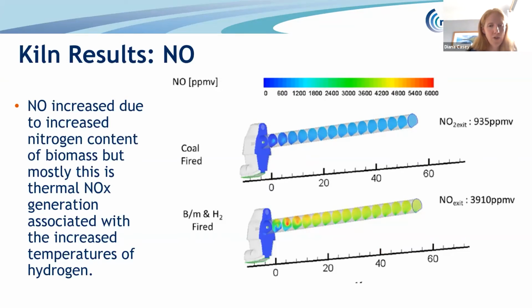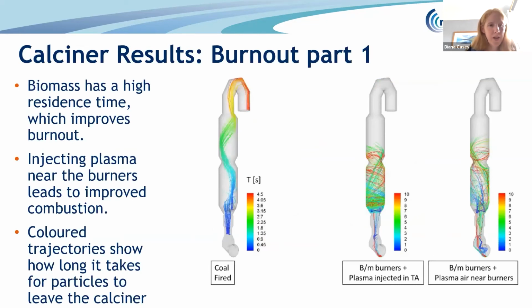I'm now going to look at some of the calciner results. This one looks at the burnout of the fuels first of all, showing the residence time of the fuel in the calciner. Again, the image on the left is the coal base case, and the two on the right show scenario 2 and scenario 3. Scenario 1 isn't shown because we're looking at the burnout of fuel particles, and scenario 1 didn't involve injecting any solid fuel into the calciner. It just used the plasma energy to gasify the biomass and then injected the gas, so there was no result for scenario 1 in this case.